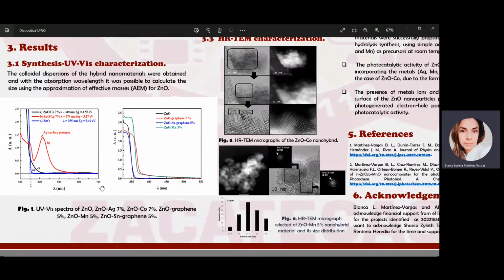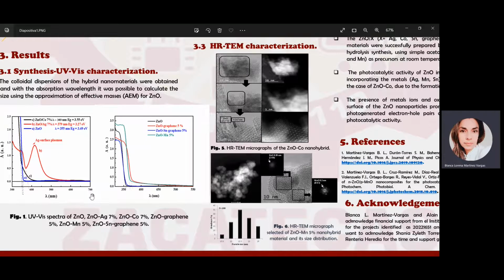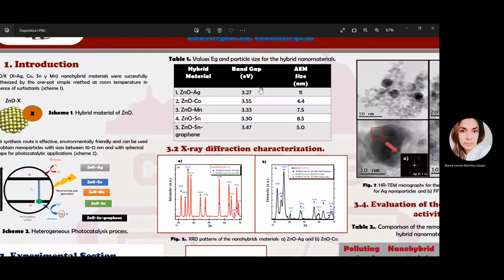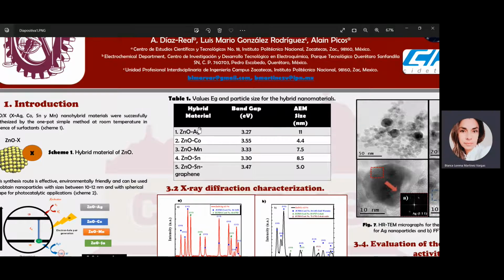In this results part, figure 1 shows the absorption spectra corresponding to each material. In all cases, the characteristic absorption edge of zinc oxide can be observed. Considering the wavelength at which the material absorbs, it is possible to calculate the nanoparticle size using the effective mass approximation, as well as the value of the band gap. These values are shown in table 1 for the different nanomaterials. The summary of this data can be seen here. The size varies from 4 nanometers to 11 nanometers depending on the different materials.